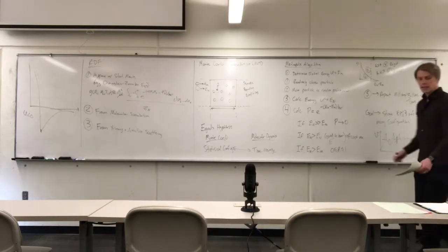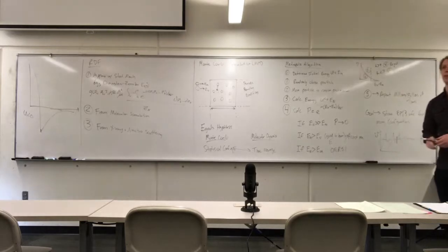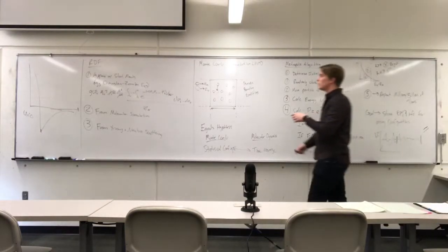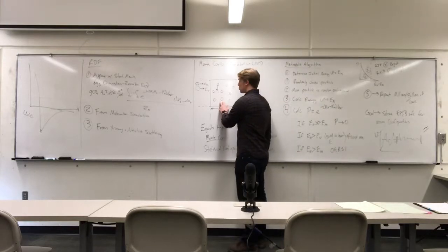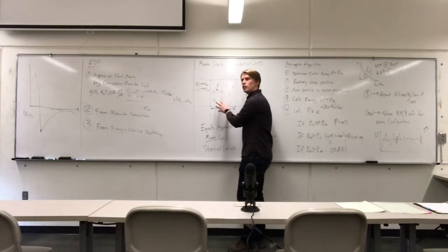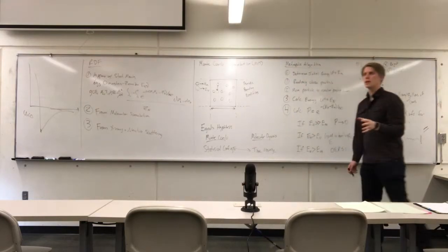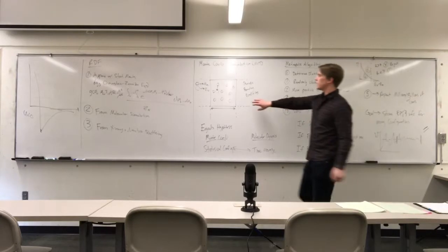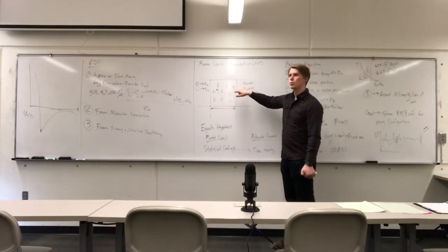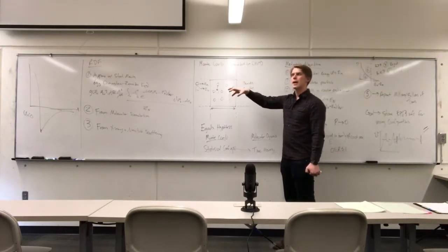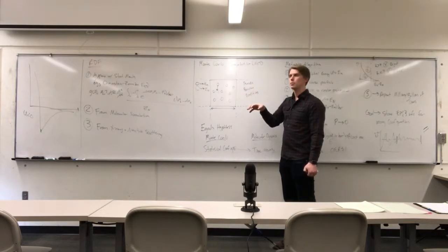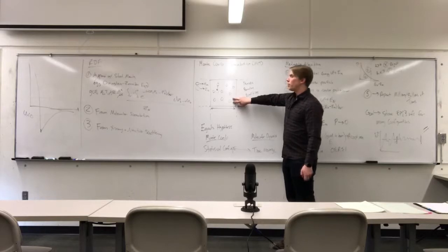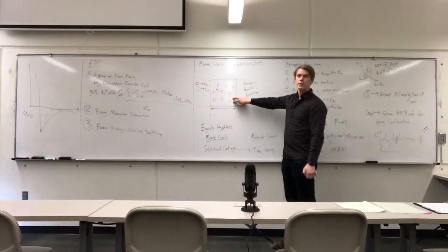So the idea here is that if we store, let's say for example, one of my students is working on a project similar to this, where he's trying to represent the scattering pattern of a fluid. I don't know if you guys were at the symposium, there's a talk on the structure of liquid 1-methylnaphthalene. This is how we get that structure: we move the particles around until we can get a better and better match of the scattering pattern that we measure experimentally, and that's how we know where the molecules are in the fluid. But his simulations, they average over 40,000 snapshots.